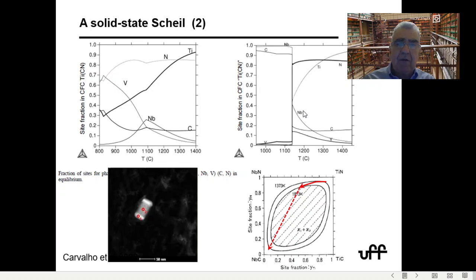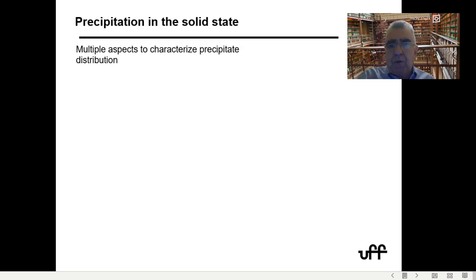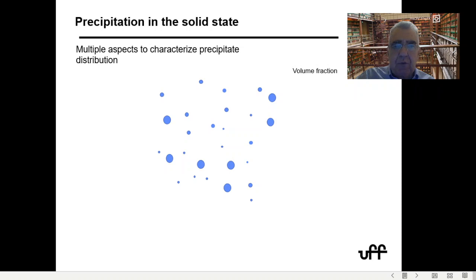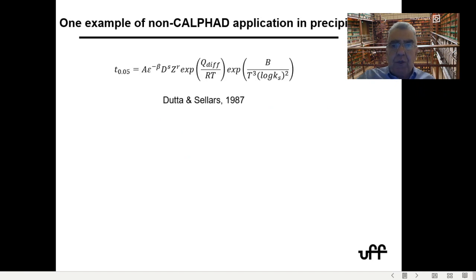So you can simulate that relatively easily by doing a SCHEIL model, so you can reproduce what's happening in these cases. Now, the problem with precipitation in the solid state, and that's why I'm not going to show you DICTRA calculations, is that there are multiple aspects needed to characterize the precipitate distribution. Reality is much more like that than a single particle, so you have to look into volume fraction, mean size, size distribution, and then you get information about spacing, and you also try to predict the effects. What people have been doing is very classical equations, in which you take the classical formula for nucleation and growth, like Dutta and Sellars did. It's very nice work, and calculate the time required to reach a certain volume fraction of precipitate.